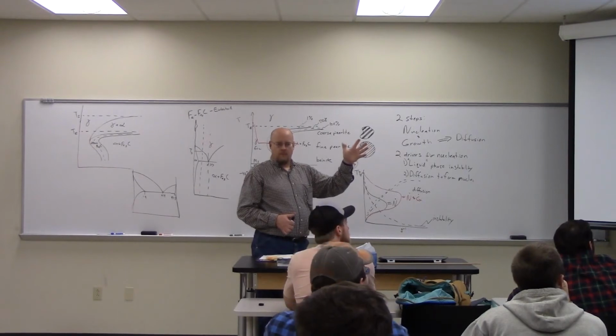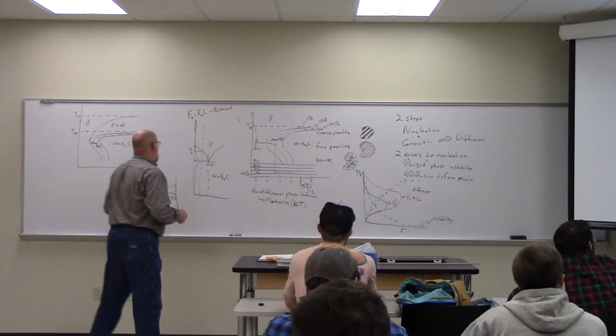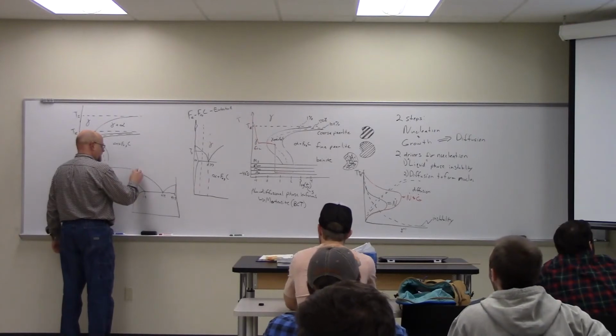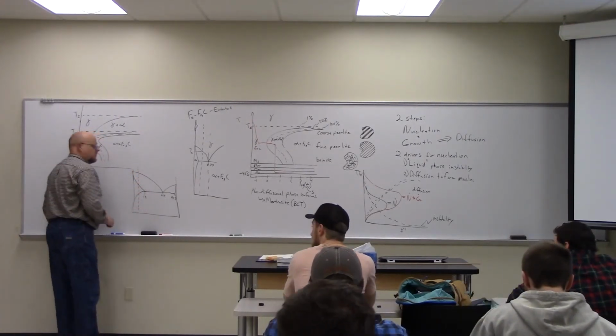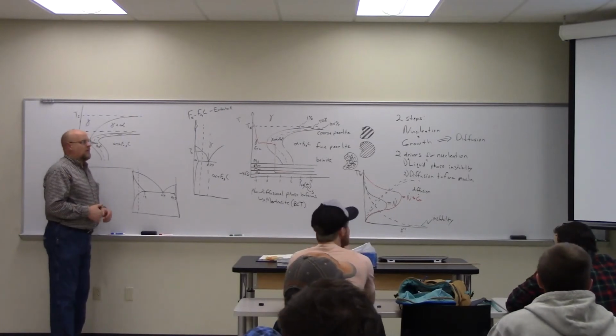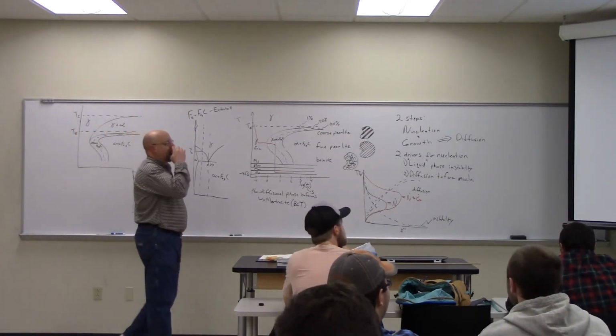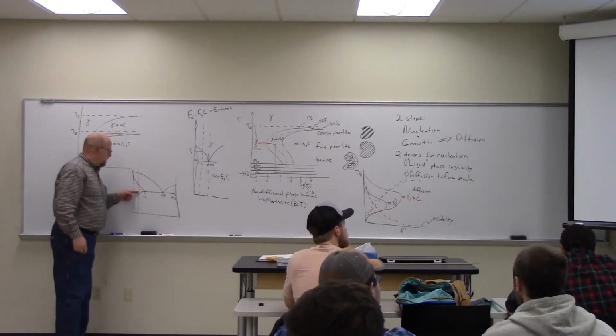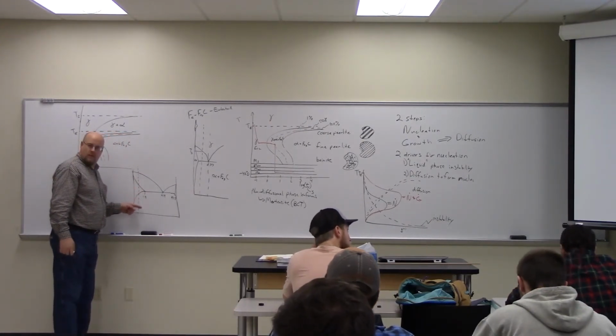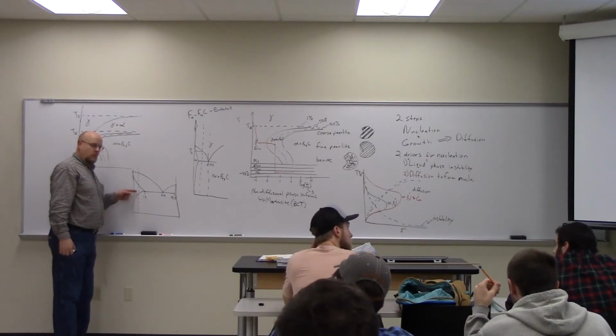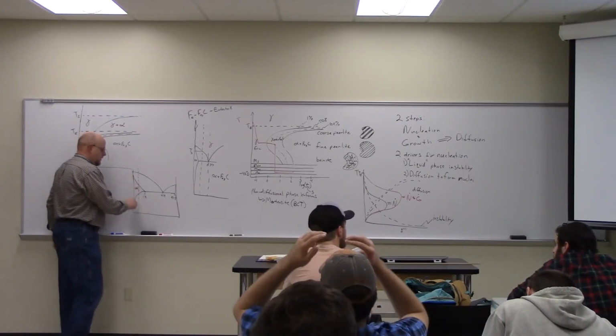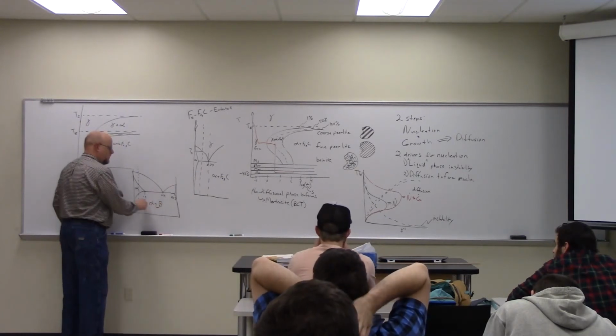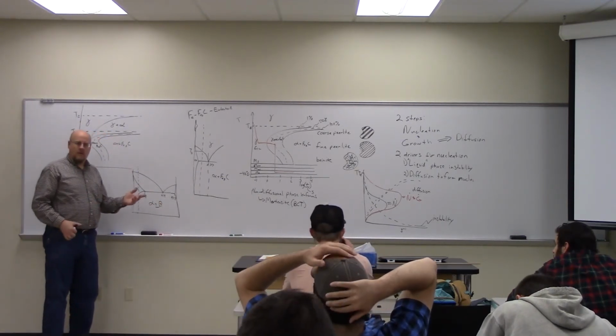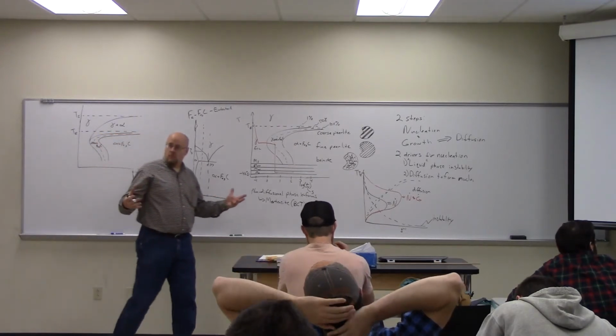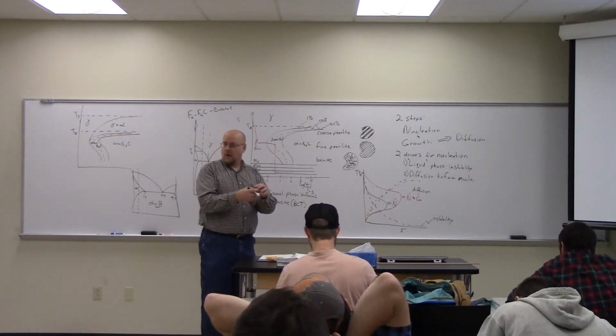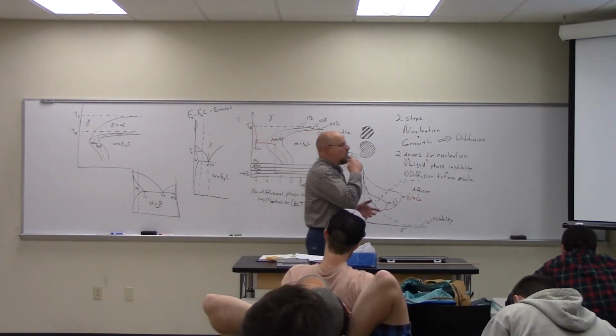Everybody understand that? Okay, so we're at a 10, 90, right? We're doing this. So we're coming down this graph, the graph right here. So we basically take this and we're cooling it down. So we're moving into this two-phase region where the alpha lead is breaking into alpha plus beta, and we're precipitating out beta. Right? So it requires that the beta, the tin atoms diffuse together to the grain boundaries, particularly, in order to form the material.